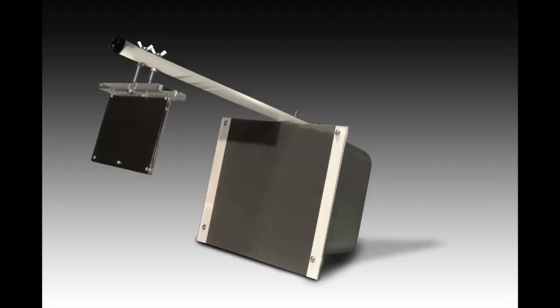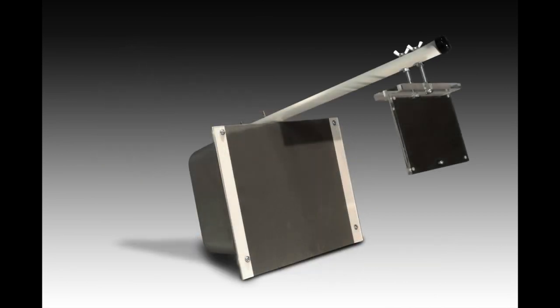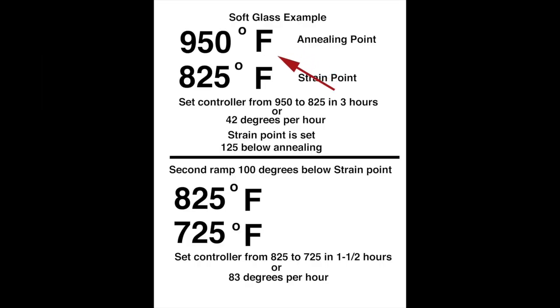How do we start an annealing profile? Well, the first step is I would follow my suggestion. When you finish a sculpture, take a look at it in a Polariscope before you put it in the annealer. If there's no strain in it, then I would start by holding it for about 1 hour at the annealing temperature. And then I would start the ramp down. And let's say it's anywhere from 1/2 inch to about 1 inch thick. I'd use about 2 to 3 hours between the annealing point and the strain point.